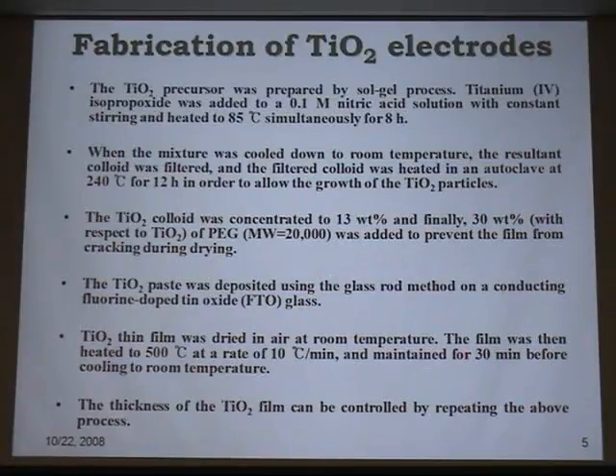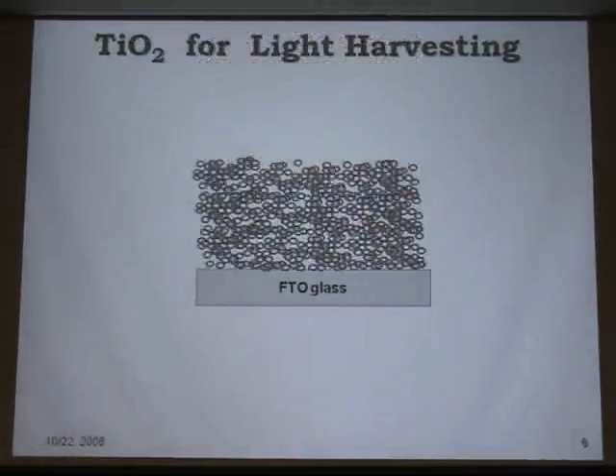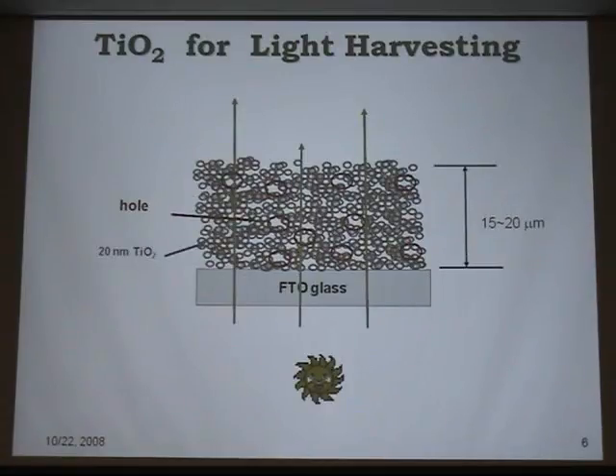And sometimes the thin film has to be coated several times in order to get enough thickness. For example, with a traditional N3 or N719 commercial dye, you need about 15 to 20 micrometers to get enough efficiency. So in other words, if you have 5 or 6 micrometers per coating, you need to have 3 coatings in order to get the right or enough amount of dye absorbed on or inside the pores.